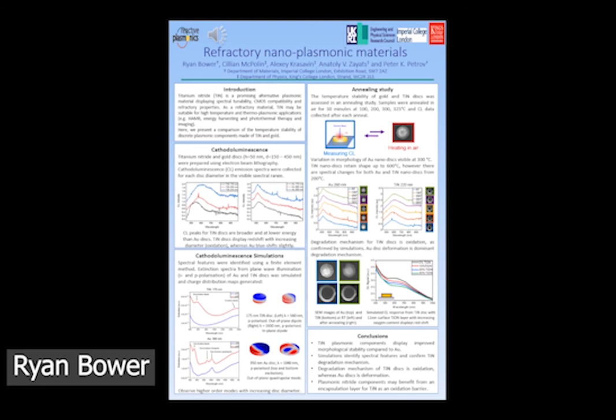In this poster, we present our work on refractory nanoplasmonic materials, where we compare the temperature stability of individual titanium nitride and gold nanodiscs in order to assess their suitability for use in high-temperature plasmonic applications. We fabricated discs of titanium nitride and gold with varying diameter using electron beam lithography, and then assessed their cathodoluminescence response, where we excite with an electron beam and collect the radiation that is emitted into the far field.